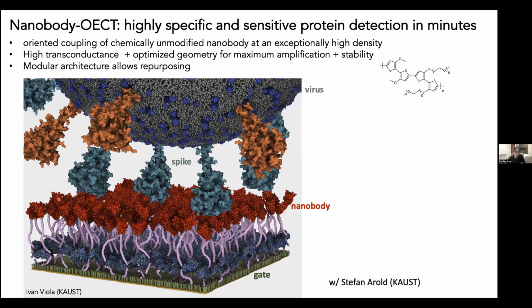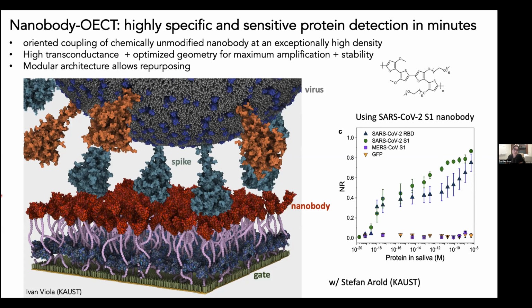Now, the sensitivity is arising, we think, not only because our transistors have very high transconductance and they have an optimized geometry for maximum amplification, but it's also because of the gate electrodes that we use, which have very dense immobilization methods where we don't really do anything to the nanobody, and you have lots of nanobodies covering the gate electrode surface at an exceptionally high density. And these are the results of the sensor for protein that we spike in patient saliva samples. So obviously these are artificial samples that we generate, but the saliva is not artificial, so that we get from volunteers. And this is the sensor response. So this is a SARS-CoV-2 sensor that we first exposed to non-target proteins such as GFP, as well as MERS-CoV S1, another coronavirus type.